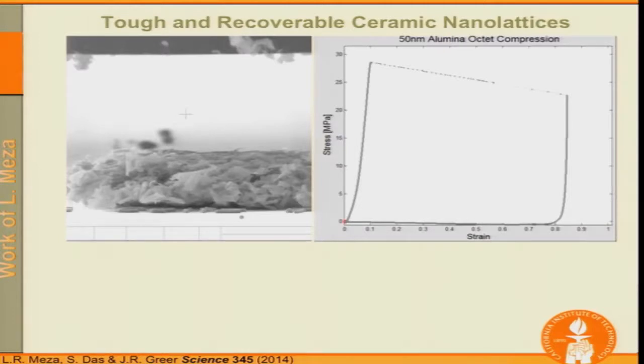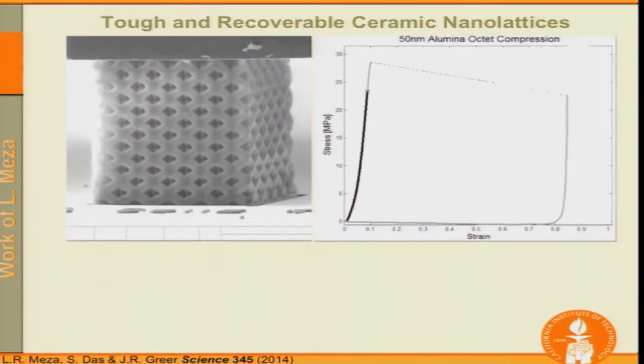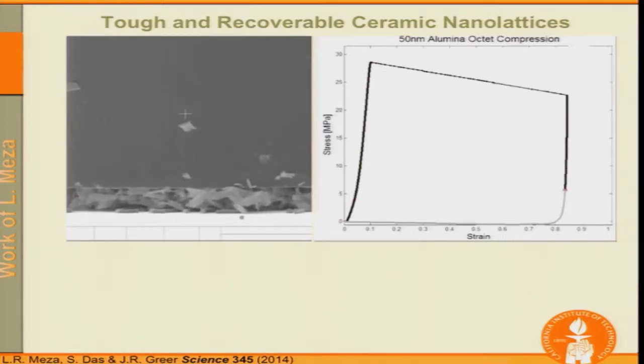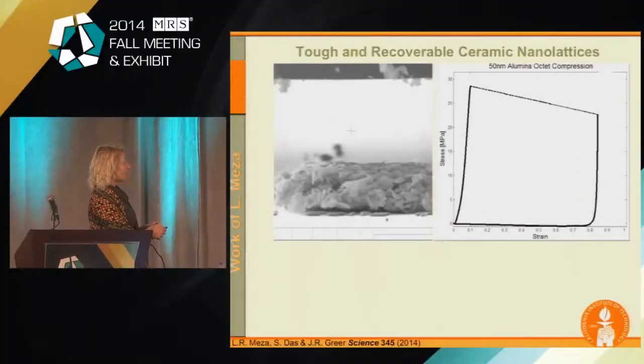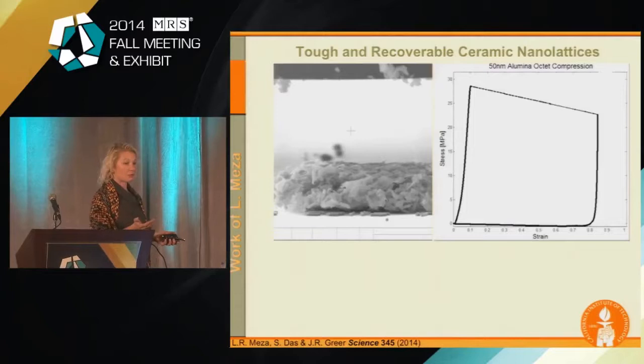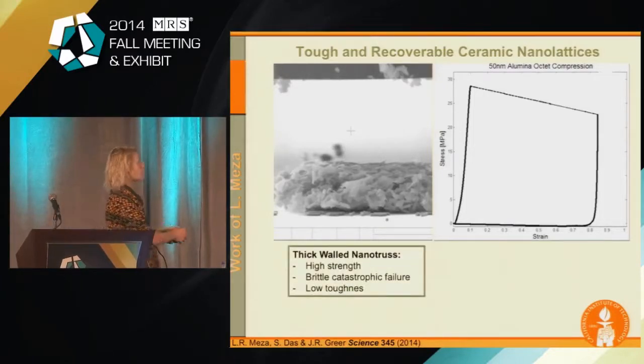Thickness in these is about 50 nanometers. That's the wall thickness. So we're already in the nanometer regime. So you look at this and you say, well, you told us that there was a material size effect, but there's nothing different. Here, I'm showing you the video one more time. So it loads, it unloads, and that's it. Nothing interesting. Well, there is one thing that is kind of neat, and that is that it's still strong.